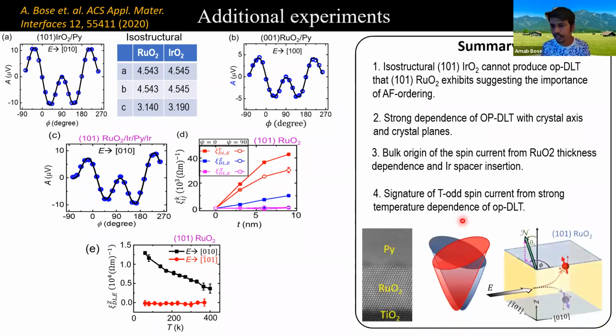So in summary, we have measured spin orbit torques in very high quality epitaxially grown ruthenium dioxide single crystal thin film permalloy bilayers. We observe strong crystal axis dependent extraordinary spin current or tilted spin current that originates from the spin split bands of ruthenium dioxide as has recently been predicted.